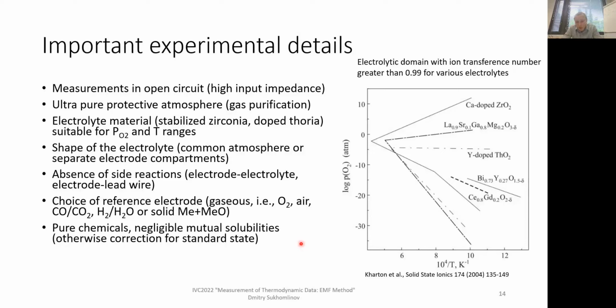Then choice of reference electrode. It might correlate with choice of electrolyte material. So we might want pure oxygen, air, or there are other options, CO2, hydrogen water mixture, or again, it can be not gaseous, it can be just solid. A mixture of metal-metal oxide, and Gibbs energy of formation of this oxide should be well known to us. Then we can use it as a reference electrode.